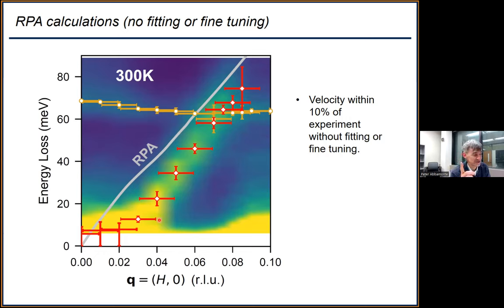There's one way in which the agreement is excellent, and that's that there is a mode. I mean, it could have happened that there was no gapless mode at all. Not everything has a demon. So the fact that you even see an excitation at all is some indication. Also, RPA is not exact, right? It's missing all kinds of effects: excitonic effects, local field factors, higher body decay processes. All kinds of stuff is missing. It would be weird if they agreed perfectly.